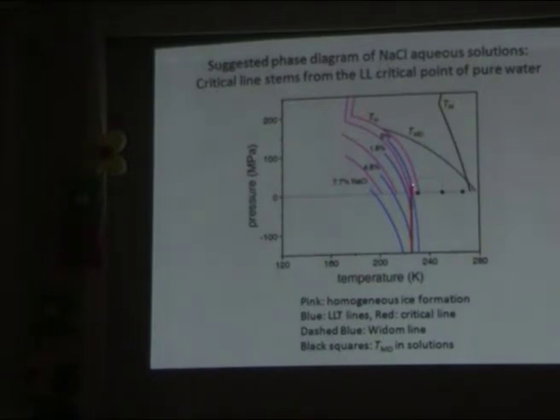This is the pure water. Blue line, our predicted liquid-liquid transition. Dash line is the Widom line, continuation of the transition. And the red line, almost vertical, is our predicted line of critical points in solutions upon change in the concentration of salt. So it is 2% of salt, the line of liquid-liquid transition terminated at critical point, 5% of salt, 7.7, and so on and so on.